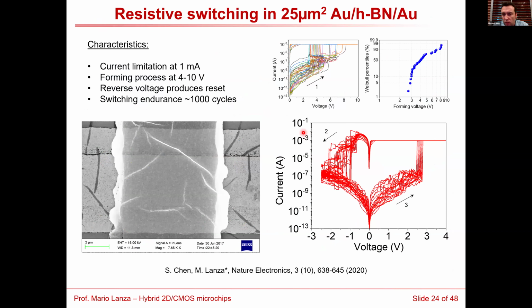You can also see the top SEM image with the wrinkles here of the device, the bottom electrode and the top electrode. The wrinkles confirm that there is boron nitride in it. We measure several devices, and this is what we observe. Low leakage current followed by dielectric breakdown.